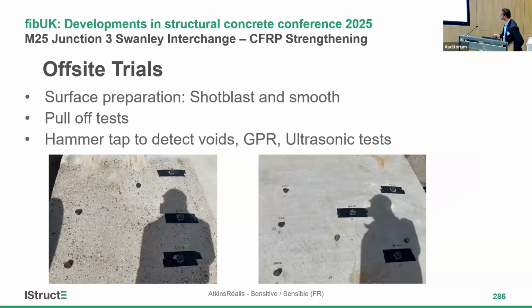Then the surface preparation: whether we had to shot blast, or whether just a smooth surface finishing of the concrete was enough. So we also carried out some pull-off tests on both the surfaces. Then a hammer tap survey was also checked along with ground penetrating radar and ultrasonic tests to see if we have any voids in the resin. Even though it's not a standard technique, we still tried to see if we could capture something, but we were unsuccessful.